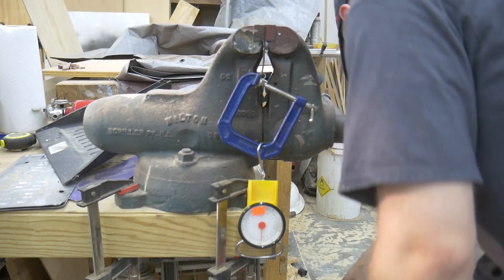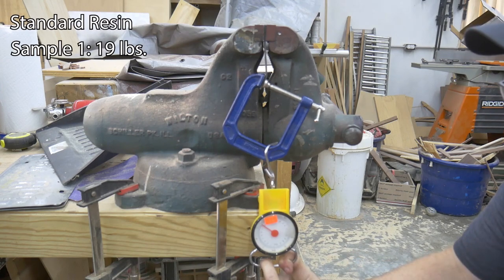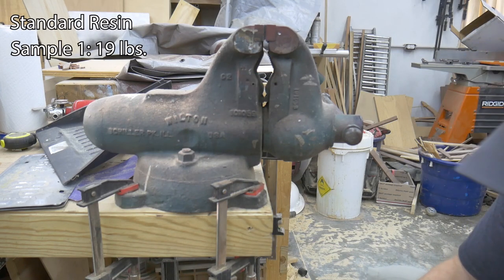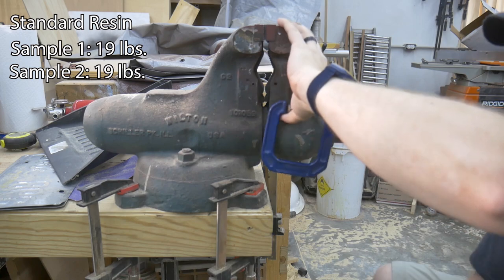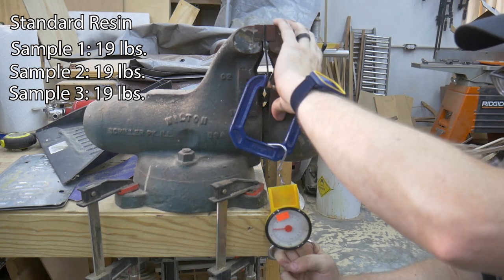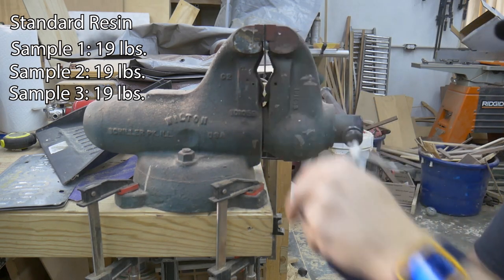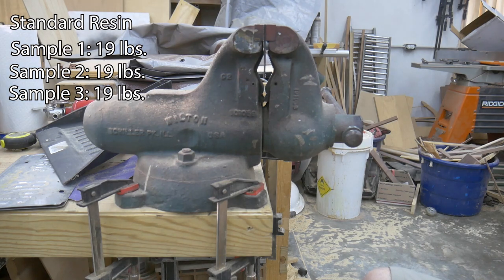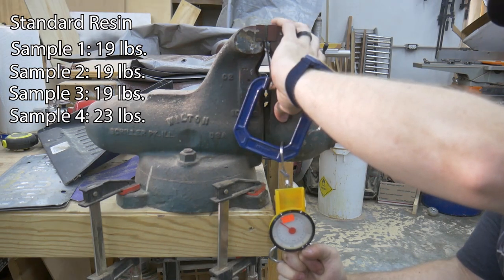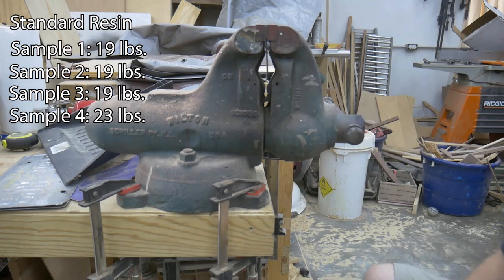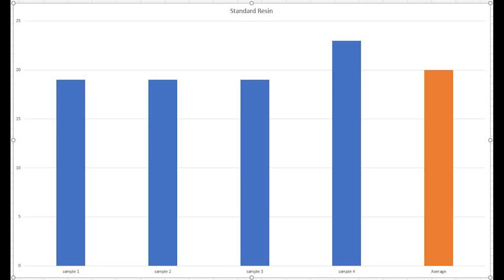First up, standard resin. Sample 1 failed at 19 pounds. Sample 2 also failed at 19 pounds. Starting to see a pattern here as sample 3 also fails at 19 pounds. Sample 4 failed at 23 pounds. The average strength for the standard resin after testing is 20 pounds.